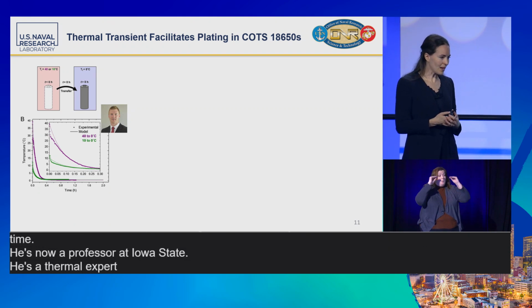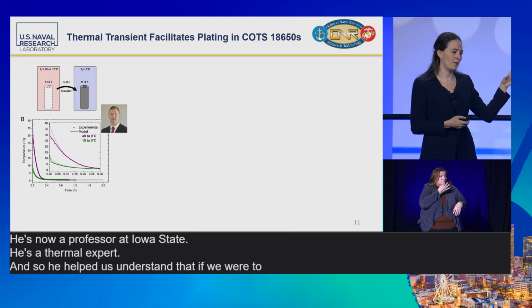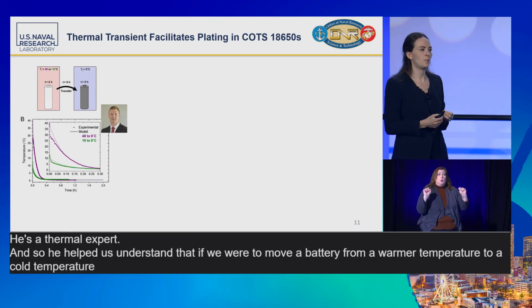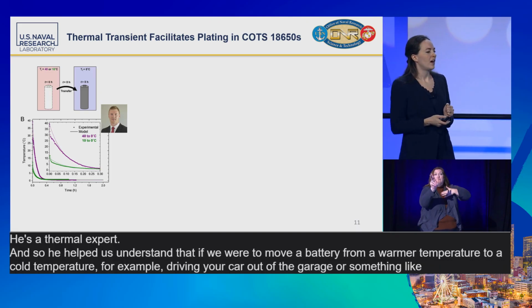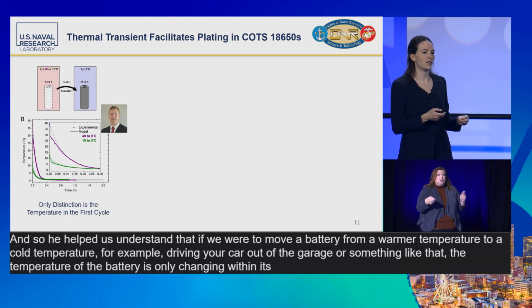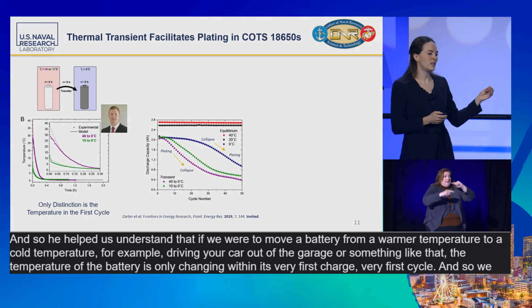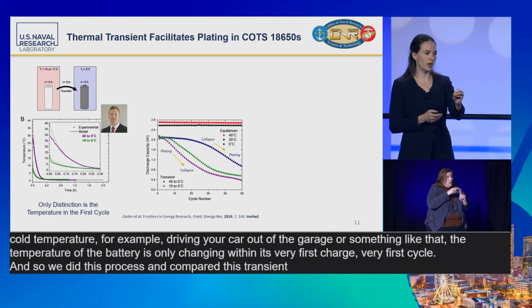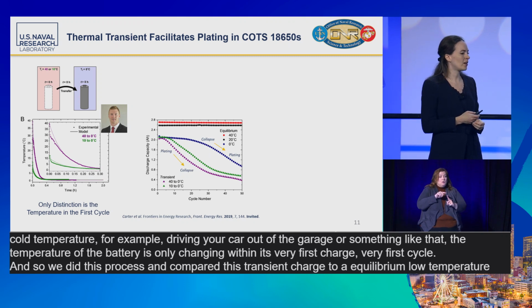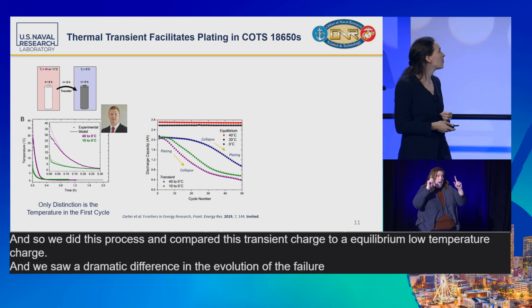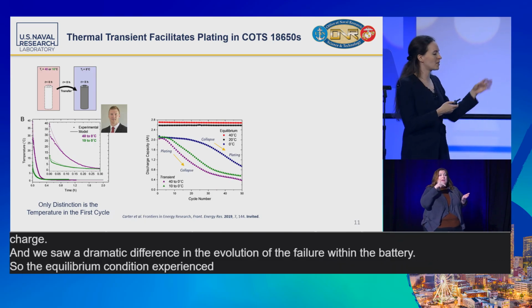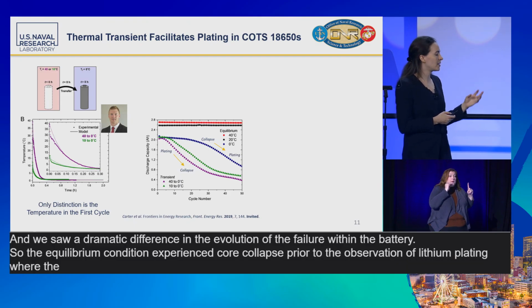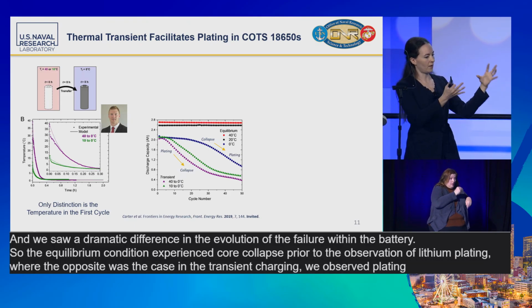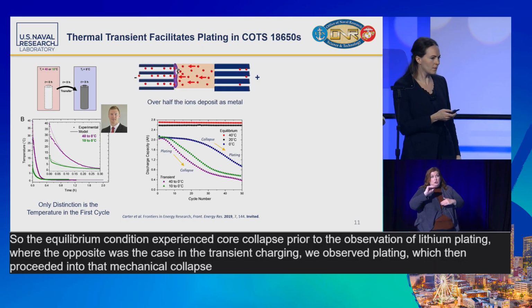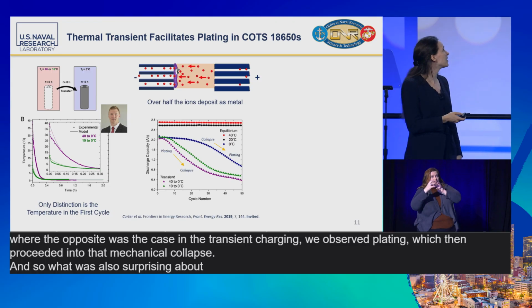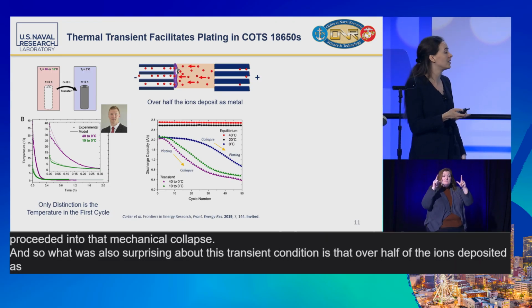He's a thermal expert. And so he helped us understand that if we were to move a battery from a warmer temperature to a cold temperature, for example, driving your car out of the garage, the temperature of the battery is only changing within its very first charge, very first cycle. And so we did this process and compared this transient charge to an equilibrium low temperature charge, and we saw a dramatic difference in the evolution of the failure within the battery. So the equilibrium condition experienced core collapse prior to the observation of lithium plating, where the opposite was the case in the transient charging. We observed plating, which then proceeded into that mechanical collapse. And so what was also surprising about this transient condition is that over half of the ions deposited as metal and did not intercalate into the anode.